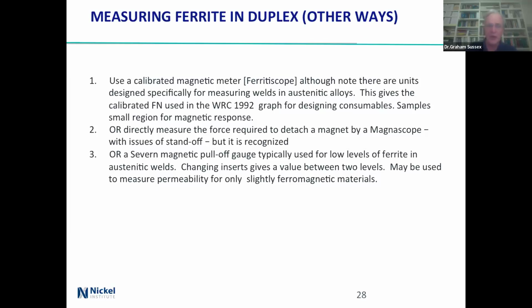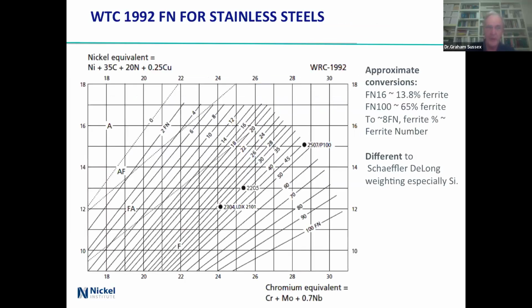Or if you're looking at really low levels, use a pull-off gauge, but that's old history, from the days when you were looking for levels of ferrite in austenitic stainless steels. This is the Welding Research Council, not WTC. Gosh, sorry. There's bound to be some slips. 1992 ferrite number. And it is not the same as the Schaeffler-DeLong weighting, especially for silicon.